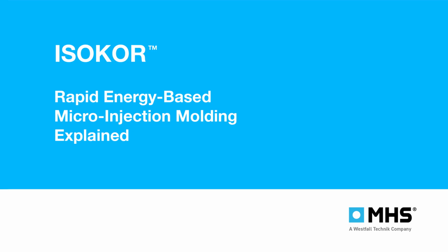According to the data in the MHS white paper, amorphous polymers like polycarbonate can be compressed by 5 to 10% in volume. Wow, that's significant. And semi-crystalline polymers like polypropylene, which have more organized molecular structures, can be compressed by 10 to 15%. So instead of acting like an incompressible liquid being shoved through a syringe, the plastic melt is behaving more like a heavy-duty coiled spring. A coiled spring is the perfect way to look at it. By squishing the molecules into that empty free volume, we are literally charging them up with potential energy. That is the massive paradigm shift of the M3 technology right there. We are entirely abandoning traditional volume-based metering, where the machine pushes a physical volume, and moving to energy-based expansion molding.